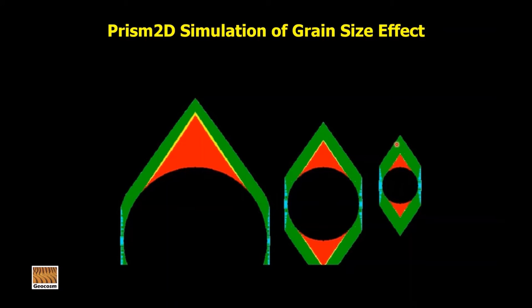And what you can see here is that the model is reproducing the fact that we grew less far along the smaller diameter grain here compared to this larger diameter grain. So why is that? Okay, let's take a look. Let's go back in time and look right here. And this is the time where this small diameter crystal achieved a euhedral form.